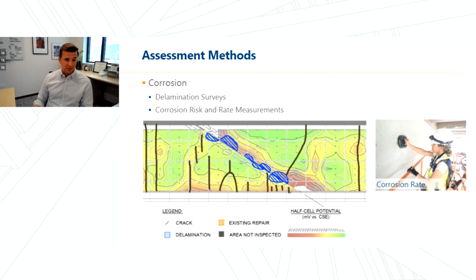You may have heard of half-cell potential, as well as corrosion rate measurements that give us a point-in-time estimate of the corrosion rate. And with these risk and rate measurements, it's important to understand and interpret these with respect to conditions, such as carbonation, cover depth, moisture conditions. These can greatly impact those measurements and how we interpret them. But nonetheless, these methods provide a snapshot in time of the condition, and they allow us to map these relative measures over the surface of the concrete.